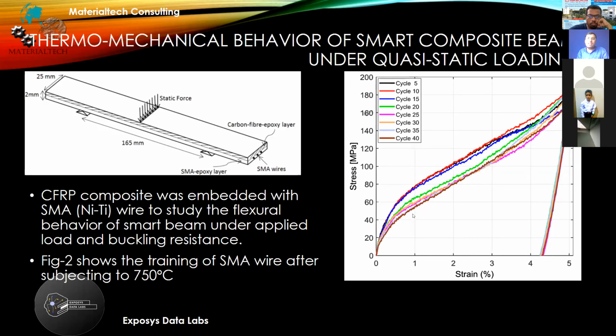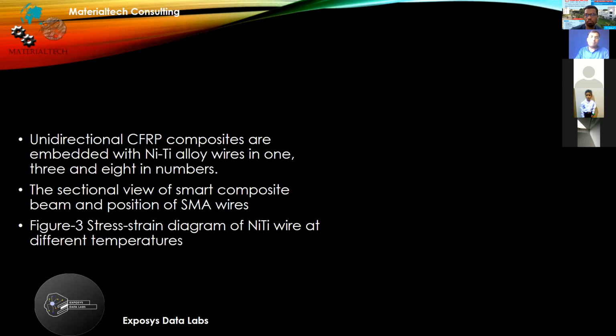We have seen the stress strain graph here for the different cycles. For 5 cycles, how it is giving the stress strain graph, for 10 cycles, 15, 20, 25, 30, 35, 40. So that means we have checked whether it is working properly for 40 cycles. And we have seen that very small deterioration from 5 to 40 cycles. That means it's giving more stability and more repeatability in memorizing the shape and returning to the original position. That's what we have observed in this study.